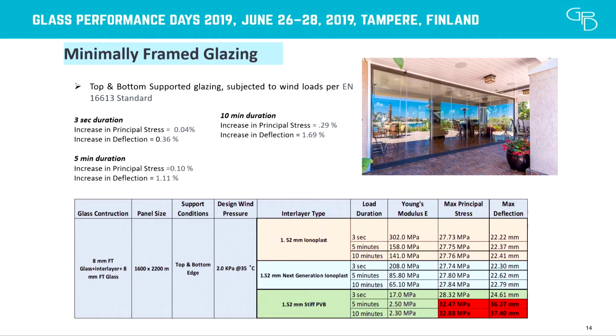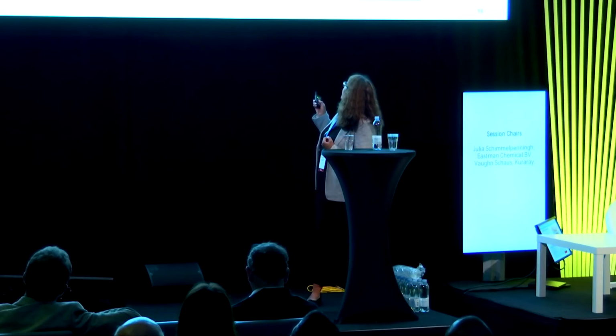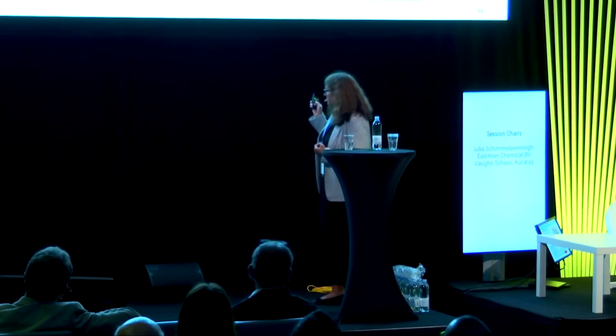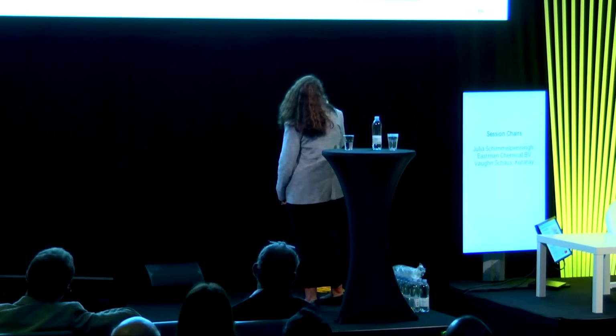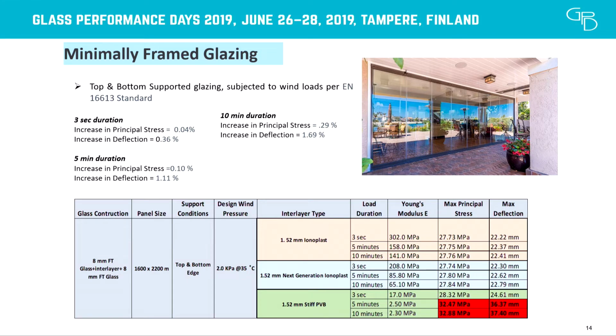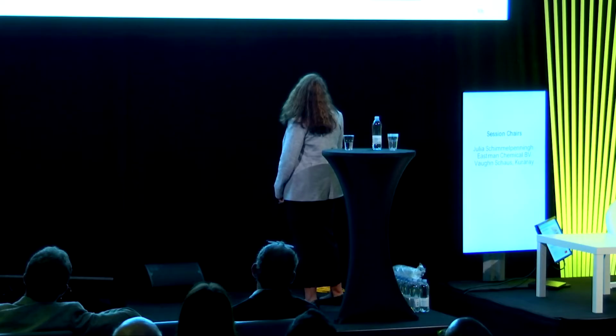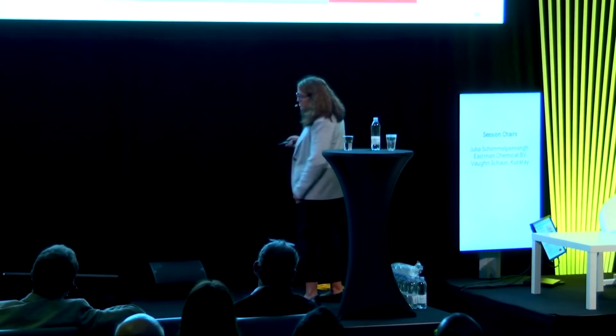So I'm just going to go through 2 load scenarios to show you. This is a minimally framed glazing system using 35 degrees C and a 2.0 kilopascal design wind pressure. I want to show that in the current Ionoplast, you have the maximum deflection and maximum principal stress. And in the next generation, you have the values for that, along with the Young's modulus. And you can see that it is a little bit higher. You have about a 0.04% increase in principal stress, 0.36% increase in deflection for the 3-second, and here are the values for the 5-minute and 10-minute. So it does have a little bit more deflection and a little bit more stress, but if you compare it to the stiff PVB, it's still much better.